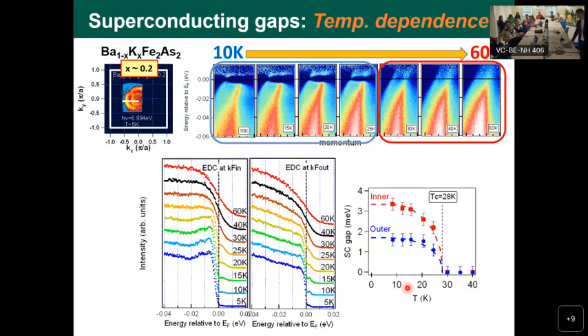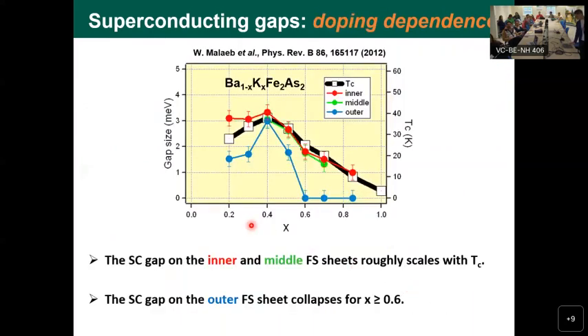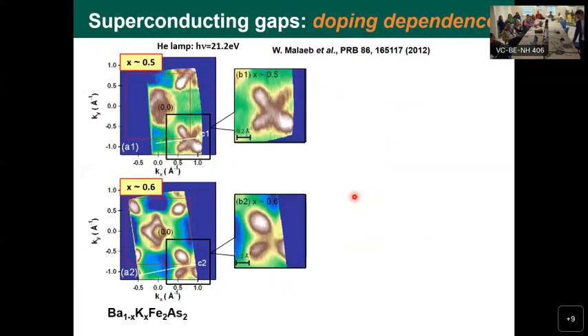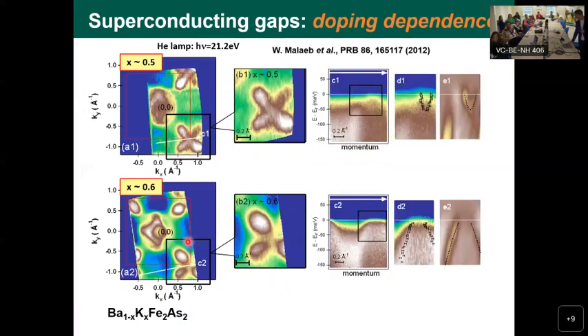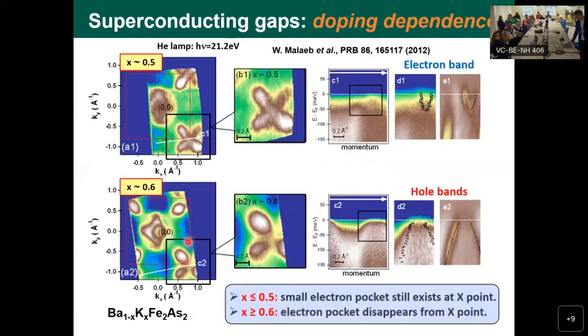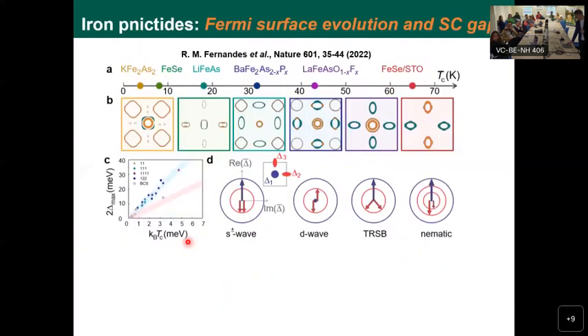So this is just an example of how we can measure the gap, but we did a full study for a wide doping region, meaning different TCs. We were investigating how the gap affects TC on different Fermi surface sheets. And we noticed that one of the Fermi surface sheets doesn't contribute. Why is that? We extended the study and investigated the Fermi surfaces, and there was some change at the Brillouin zone corner.